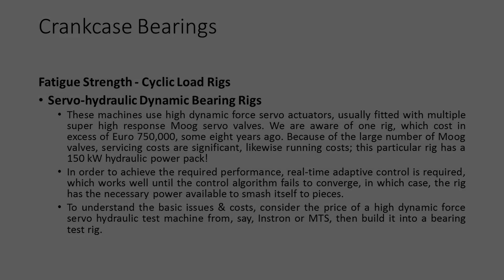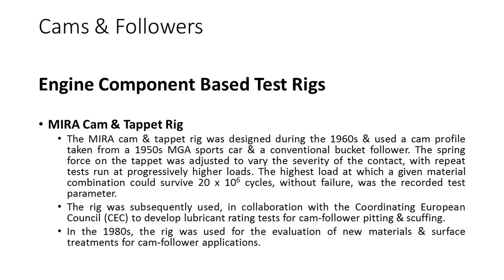The MIRA cam and tappet rig was designed during the 1960s and used a cam profile taken from a 1950s MGA sports car and a conventional bucket follower. The spring force on the tappet was adjusted to vary the severity of the contact, with repeat tests run at progressively higher loads. The highest load which a given material combination could survive 20×10⁶ cycles without failure was the recorded test parameter. The rig was subsequently used in collaboration with the CEC (Coordinating European Council) to develop lubricant rating tests for cam follower pitting and scuffing, and in the 1980s for evaluation of new materials and surface treatments for cam follower applications.